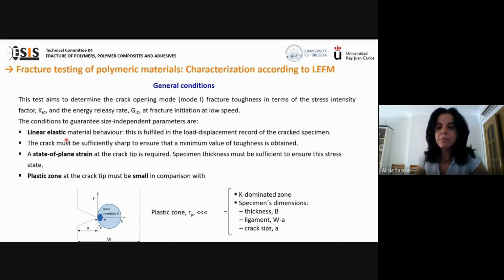The crack of the specimen must be sharp to ensure a minimum value of the fracture toughness. A state of plane strain at the crack tip is required, so the thickness must be large enough to guarantee this state. And the plastic deformation at the crack tip, shown in dark blue in this plot, must be very small in comparison with the stress intensity factor dominated zone, that is the area ahead of the crack tip and shown in light blue in this plot, and specimen's dimensions such as the thickness B, the ligament defined as the width minus the crack length, and the crack length a.